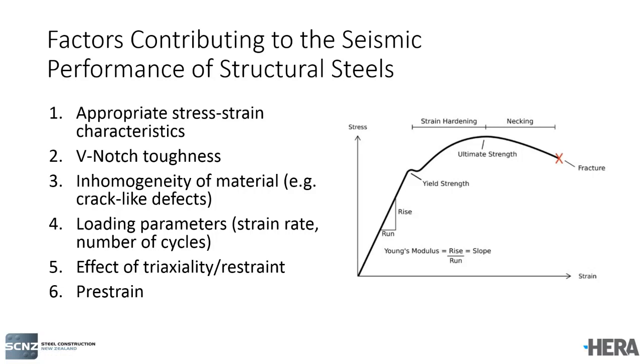So what are some of the factors that contribute to the seismic performance of structural steels? Well, the stress strain characteristics of the steel have a bearing on its performance, and we'll touch on that in the next slide. The V-notch toughness of the steel also impacts its seismic performance, and we'll talk in a bit more depth about that later. Other factors such as the presence of crack-like features in the steel can also affect the seismic performance. Weld defects can introduce crack-like features. You can also get inclusions in steel that are rolled in during the rolling process.